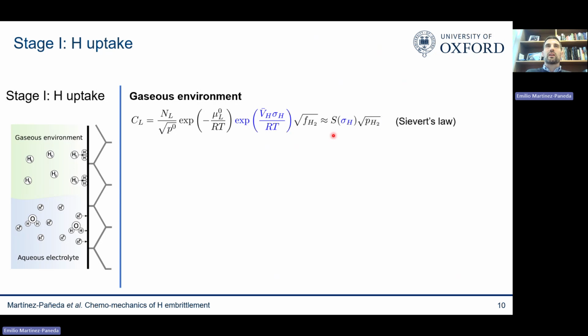One thing to be careful of is that this material solubility depends on the hydrostatic stress. You can show this easily here—this blue term has an exponential with hydrostatic stress inside it. So the coupling with mechanics is very strong, and normally we measure the stress-free solubility in a permeation test. One has to be careful that the stress-free solubility must be enhanced with mechanics if you want to accurately predict the concentration of hydrogen ahead of stress concentrators such as cracks.